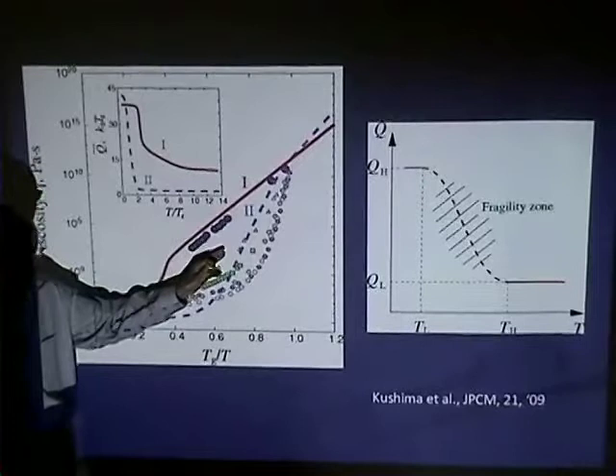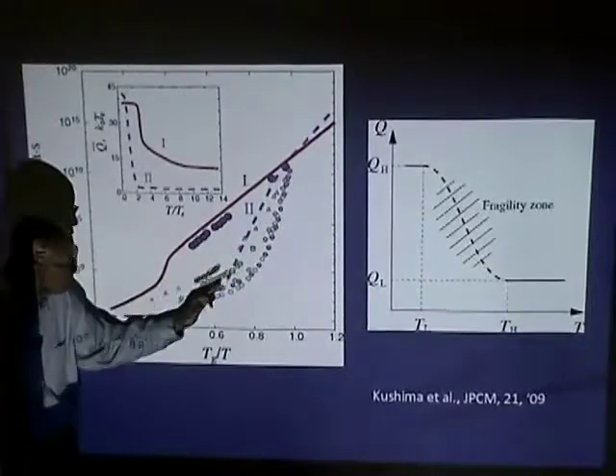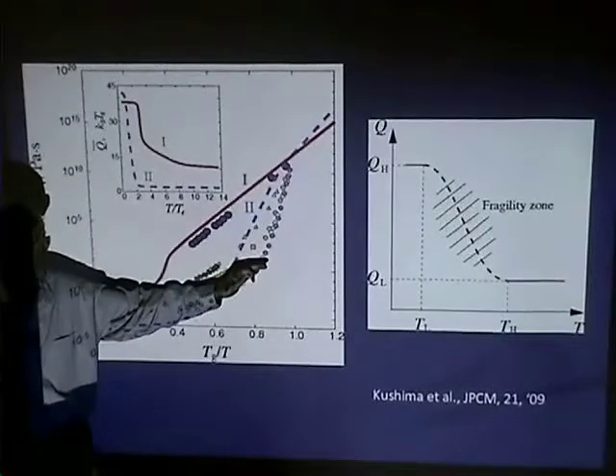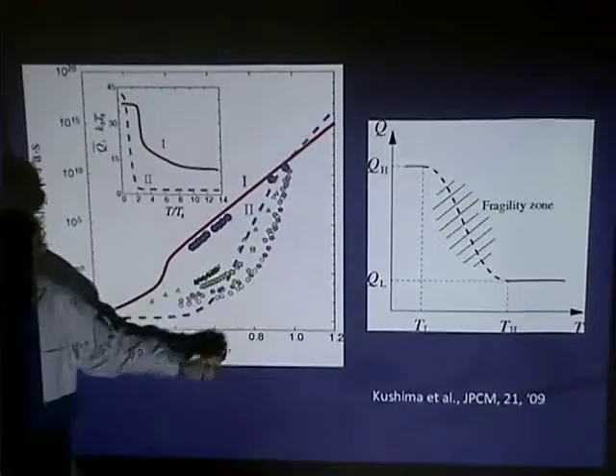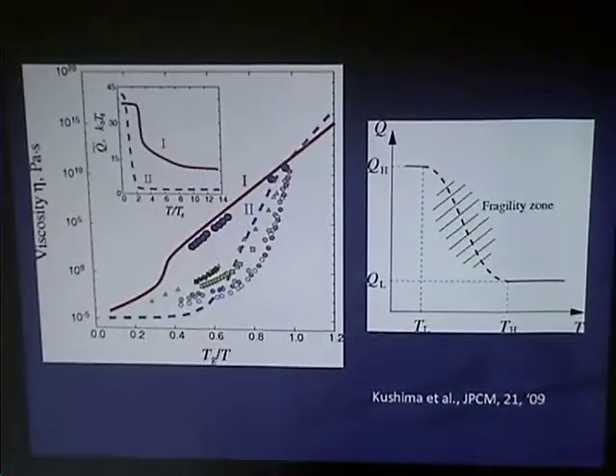And in fact it did a better job in pulling this curve closer to where the Green-Kubo method gave us. So we think that there is room for an Adam Gibbs-like statement, but at this point we're not saying anything too precise about that. But I think definitely configurational entropy could play a role - configurational entropy - and test that idea, at least in certain regimes where you can be liberated.